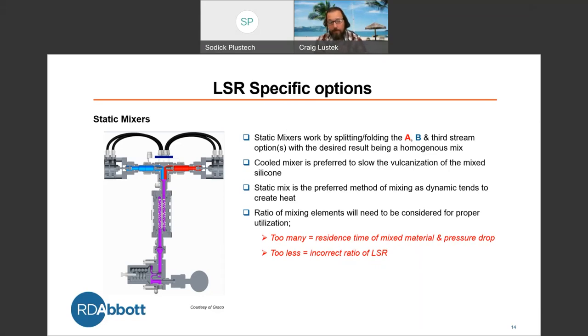And for this example of Graco, this is their cylindrical static mixer. So you can fit as many as 15 smaller plastic elements in here. Now, if you're running a higher viscosity material, you might have a pressure drop across the face. So you might not get a good reading on your pressure regulation gauge. Versus if you have two less static mixers, you're getting an incorrect ratio of material. You're not getting a good homogeneous mix.